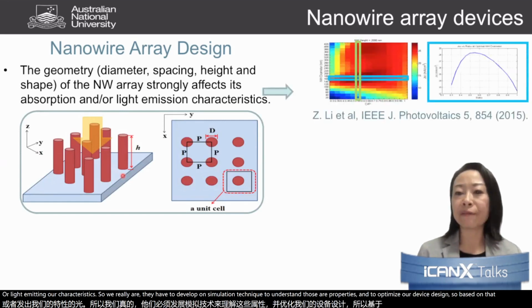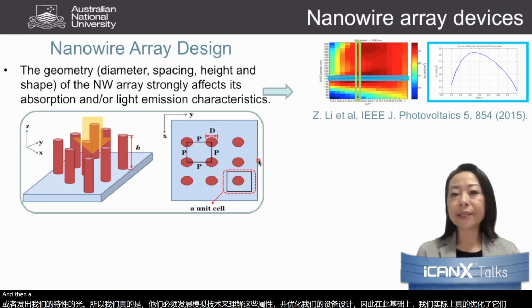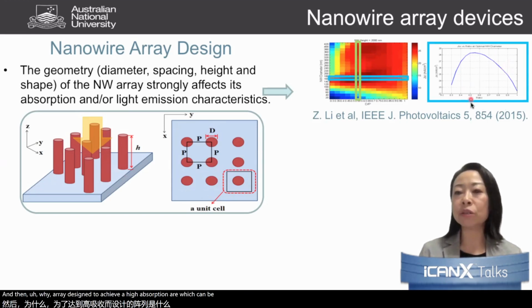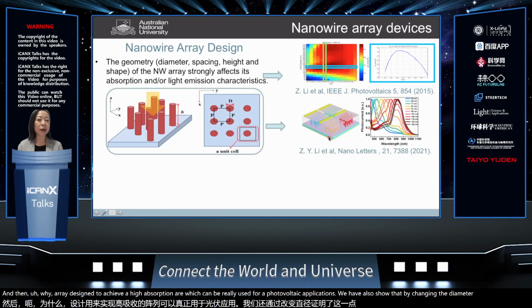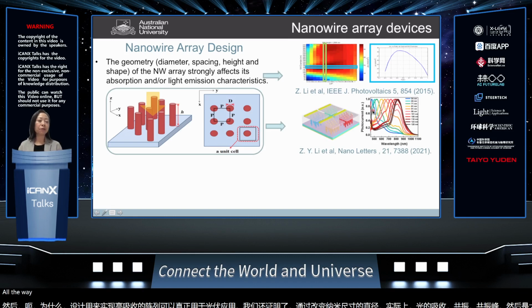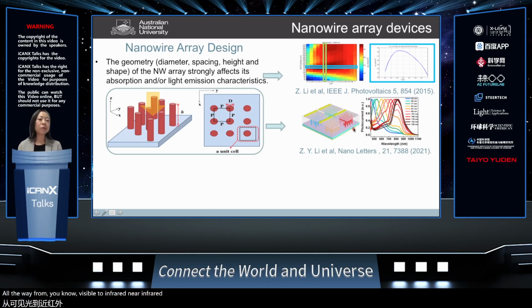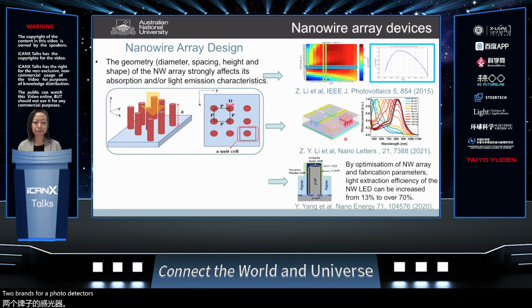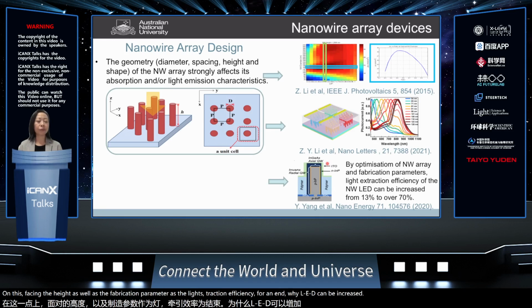Based on that, we have optimized the nanowire array design to achieve a high absorption, which can be used for photovoltaic applications. We have also shown that by changing the diameters of nanowires, the light absorption resonance peak of nanowire arrays can be tuned all the way from visible to near infrared. And then using this technique, we have demonstrated multi-wavelength, broadband, dual band photodetectors. We have also found that if we optimize the nanowire array design, namely the diameter, the spacing, the height, as well as the fabrication parameters, the light extraction efficiency for nanowire LEDs can be increased significantly.